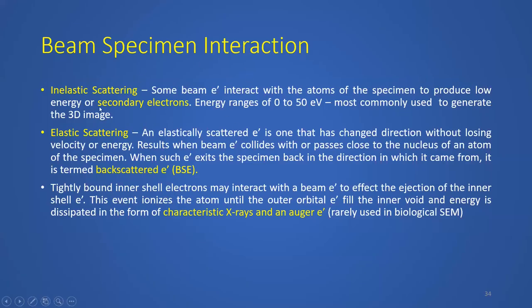Okay, so as a result of this interaction with the beam and the specimen, you have different kinds of scattering. You have inelastic scattering, where the electron beam loses some energy. So these are very low energy electrons, typically 0 to 50 electron volts, and this is commonly used to generate the 3D image. And these come from closer to the surface of the specimen.